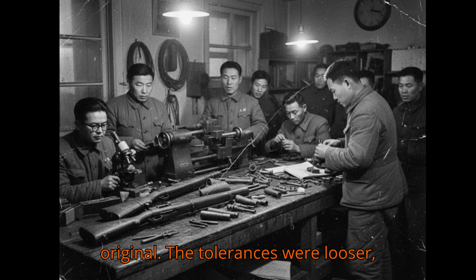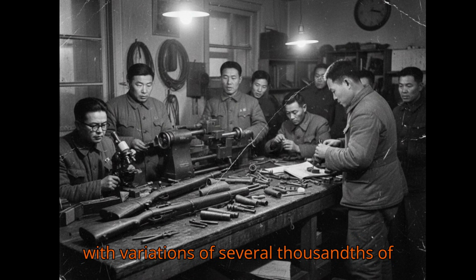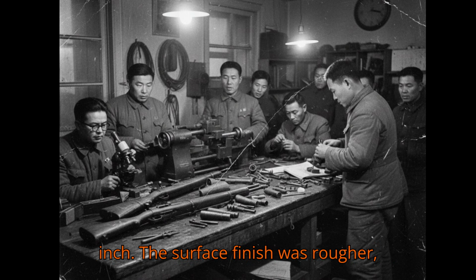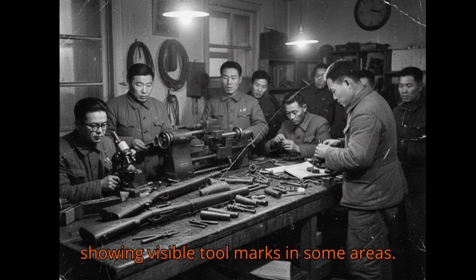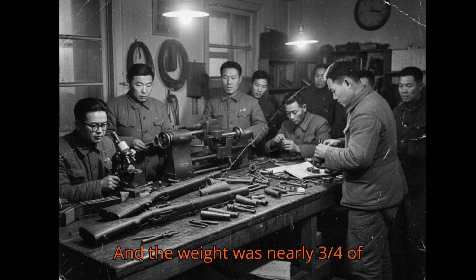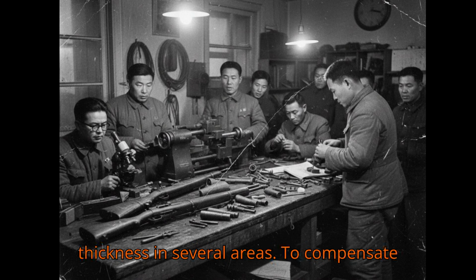The tolerances were looser, with variations of several thousandths of an inch in areas where the American receiver held within 1/1000th of an inch. The surface finish was rougher, showing visible tool marks in some areas, and the weight was nearly 3/4 of a pound heavier than the American receiver, as they had increased wall thickness in several areas to compensate for the uncertain steel properties.